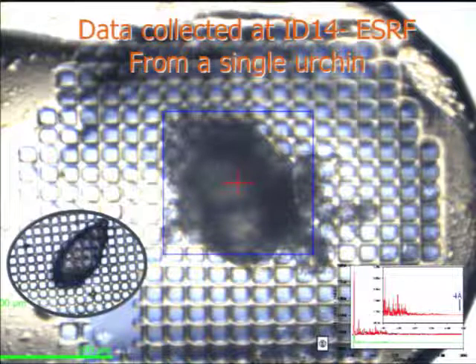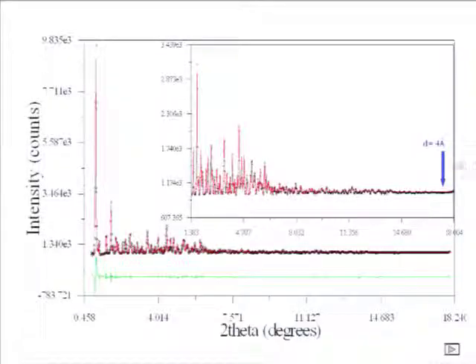And then there is a new methodology in protein crystallography. In order to avoid cryocooling, people try to use humidifiers in order to avoid dehydration of the sample and collect data at room temperature. So Yves Vattier isolated one urchin, one bunch of needles, put it in this nice holder, and in front of an area detector at ID14 at the ESRF, which is a protein crystallography beamline, he collected data at room temperature, which extend up to 4 angstroms resolution.